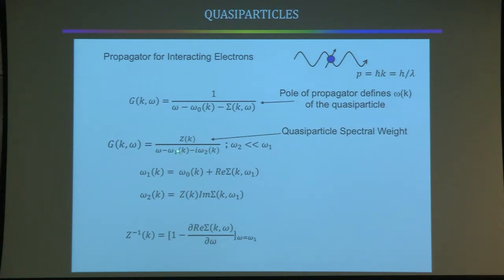And then if you do so, you can solve in this approximation where the imaginary term is much less than the real term, and get an approximation for this Green's function. When you do that, you end up with a numerator above the denominator, which is less than 1. That's called a quasi-particle weight. I'm going to talk about that a good deal in the rest of the talk. You can think of it as the amplitude of this wave function if you want to think in Schrödinger-like wave functions. Or if you're a self-energy person, you can think of it in terms of the derivative of the real part of the self-energy. Or if you're an effective mass person, the effective mass is related to this parameter.